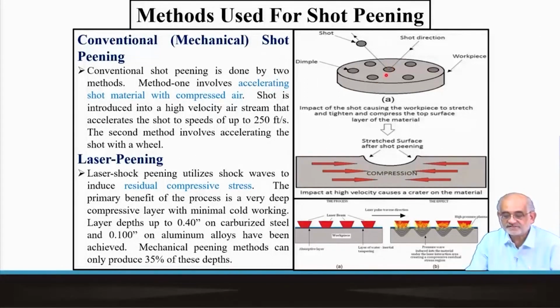Now, this is a single impact, but if I have multiple such impacts, each one of them will create certain dimples or dents. Now, if these dents are throughout the surface and uniform, then obviously we can create a surface which will have uniform deformation throughout up to limited depth. Since I told you that the diameter of the sphere that's hitting is hardly 0.5 millimeter, you may expect not even 0.1 or 0.2 millimeter depth of deformation region.